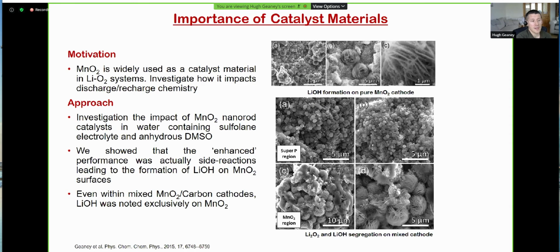and looked at manganese oxide nanorods that we formed very straightforwardly in a solution process. And what we found was these products started to form after the discharge. These were very large lithium hydroxide side products that had formed on the manganese oxide cathode. So as I said before, these were actually giving us capacity during the electrochemical cycling, but it wasn't reversible. So it was killing our long-term stability, but was giving us capacity in the first place.